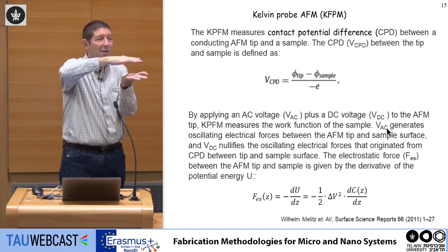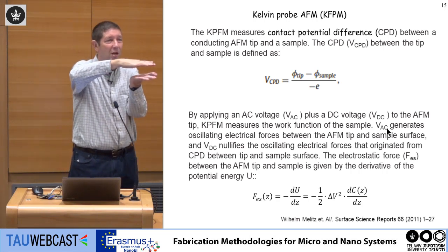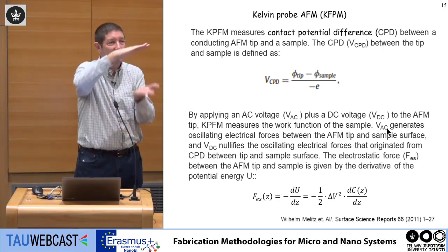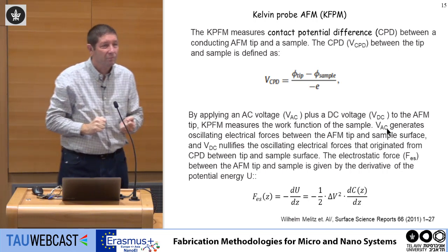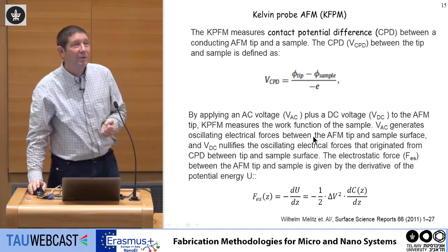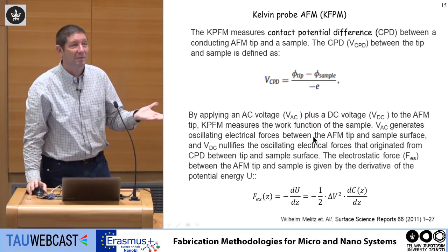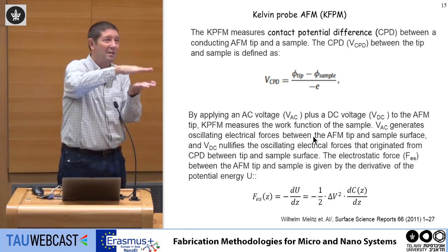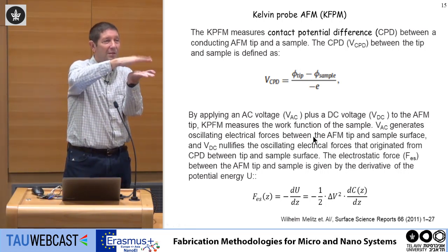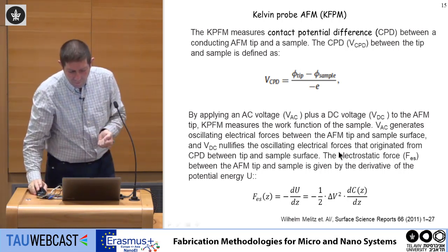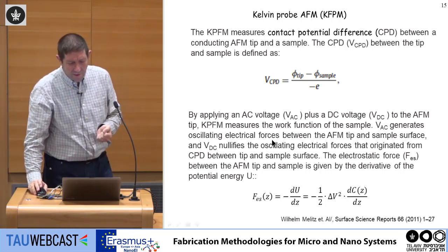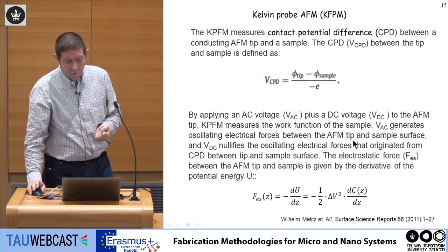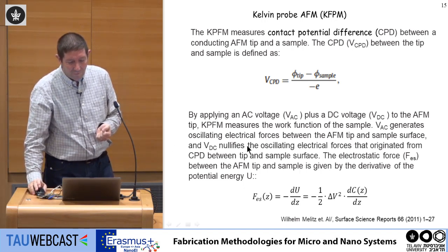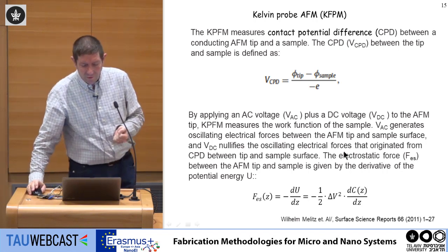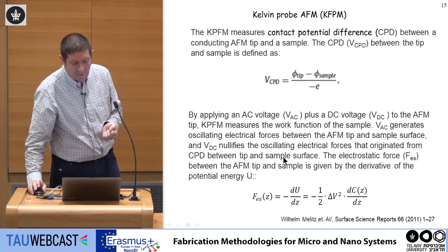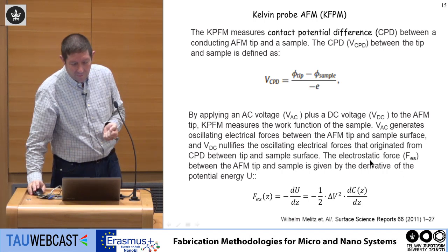We know the force between the plates depends on the charge, so the AC voltage is generating the oscillations. Because of the oscillations, I'm changing the capacitance, since the capacitance depends on the distance between the plates of the capacitor. So VAC generates oscillating electrical forces between the AFM tip and the sample surface, and VDC nullifies the oscillating electrical forces that originate from the CPD between the tip and the sample.